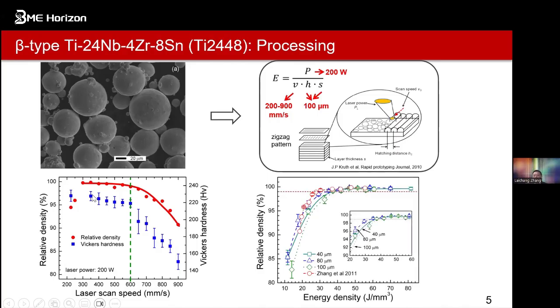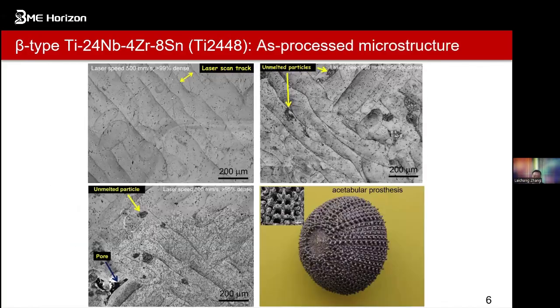But we try to bring this into industry, for commercialization. That's why we try to get a large processing window to make the parts with a high relative density of more than 99%. So we produced a lot of different parameters so that we can find the relationship with the energy density. We can find that for an energy density of roughly 33 joules per cubic millimeter, we can produce the parts with 99% density. Of course, we can still consider the microstructures of the produced parts, in three representative conditions.